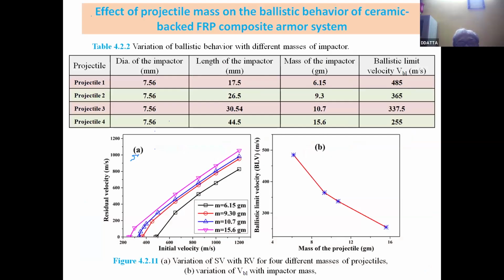The effect of the projectile mass. Here the projectile mass has also been tested. What happens if we change the projectile mass? For that we kept the diameter the same, but the length is changed, and accordingly the mass is changed. As the mass increases, ballistic limit velocity decreases. When it was a low mass, 485 meters per second is the velocity. But when it is 15.6 gram, slightly more than double, 2.5 times almost, 255 meters per second is the ballistic limit velocity. So this is the plot.